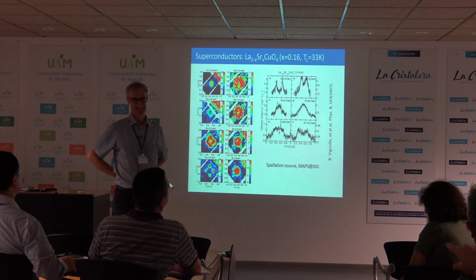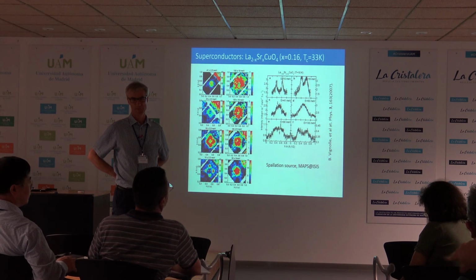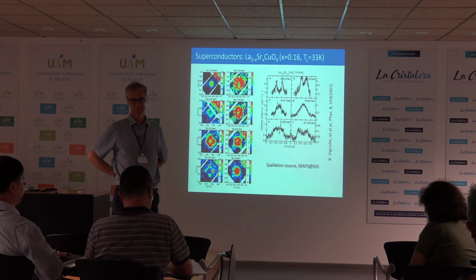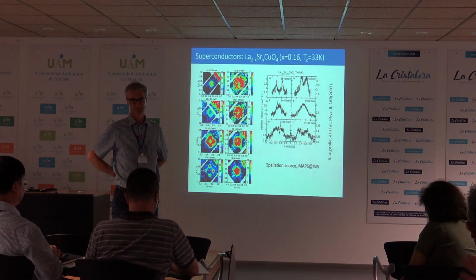Therefore you see these very sharp, low energy features that are not present at this doping level in, let's say, YBCO. But at high energies, and even at intermediate energies, you wouldn't be able to tell one from the other. LSCO looks just the same. It's indistinguishable.